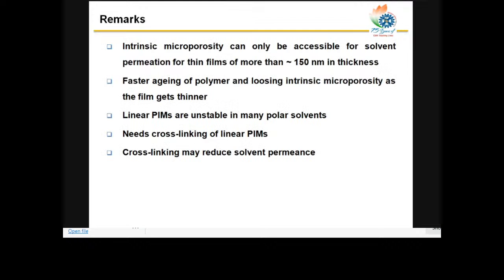So in a nutshell, the intrinsic microporosity was only accessible to solvent permeation for a thin film of more than 150 nanometers thickness. Below 150 nanometers, the intrinsic microporous structure was not accessible for membrane separation, and faster aging of the polymer, with loss of the intrinsic microporous structure, was noticed as the film gets thinner. Linear PIMs are unstable. The polymer we used in this study was a linear polymer, so it was soluble in polar solvent. This membrane is therefore not practically useful for separation of polar solvent. We can do cross-linking, but cross-linking will again reduce the solvent permeance. So finally, the drawback from this study was that a linear polymer membrane is not useful for organic solvent separation.